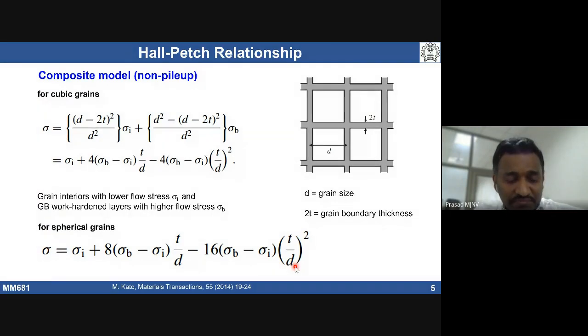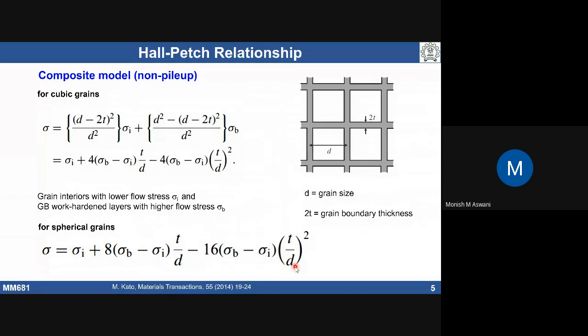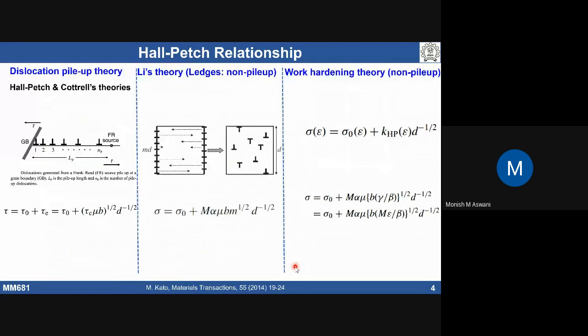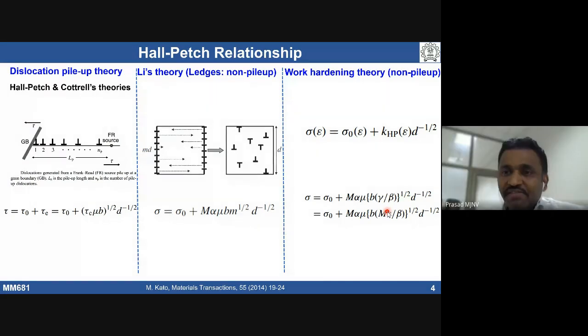Sir, in the work hardening theory, you said that dislocations can get trapped, right? So materials with low SFE will trap more and more dislocations, and hence you can see that effect in the relationship you just showed. That dislocation trapping effect will be more in lesser stacking fault energy materials. Yes.